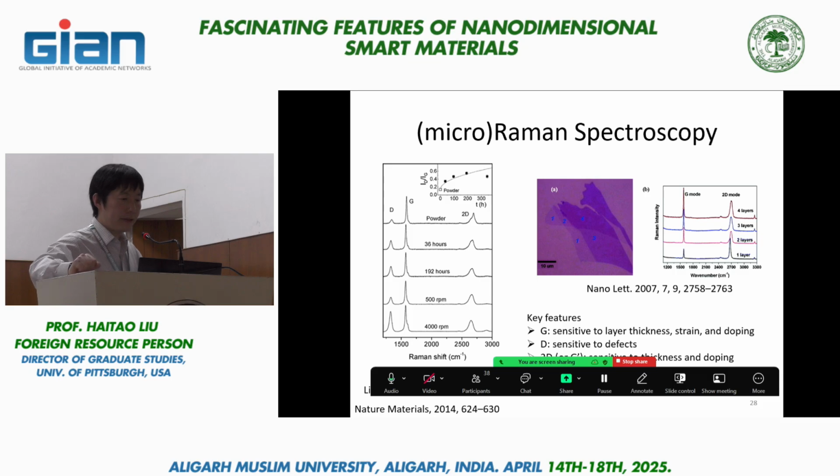So, having said that, I want to show this optical photograph. The photograph in the middle is an optical photograph. You see this purplish color. This is a signature color you would get from a silicon wafer with about 285 nanometer of oxide thickness.